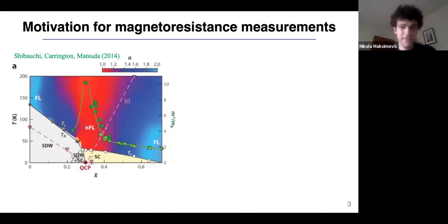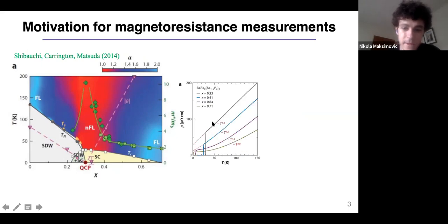So of course, here's the motivation for magnetoresistance measurements. I've plotted here the very famous phase diagram of the phosphorus-doped Barium-122 compound. Probably the most interesting thing about this phase diagram is that the material is a high temperature superconductor. And I think the second most interesting thing is the behavior of the electrical resistivity in the normal state. In particular, as you dope the system away from the antiferromagnetic phase boundary, there's a qualitative change in the temperature-dependent resistivity. This is maybe more clearly seen in resistance versus temperature traces, where you can see a change from T linear dependence of resistivity to more T squared as we dope away from antiferromagnetism.